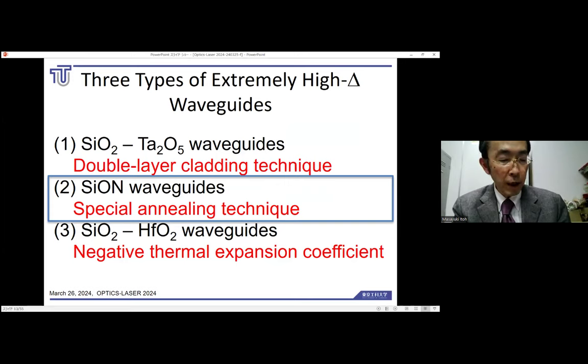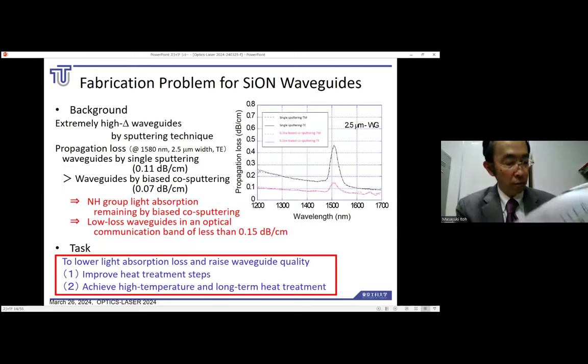Next, I will discuss silicon oxynitride waveguides. Silicon oxynitride waveguides have a long research history. However, let us briefly review the history of our research to date. We have been studying extremely high delta silicon oxynitride waveguides fabricated by sputtering and when comparing optical properties by the deposition method. If we take the wavelengths on the horizontal axis and the propagation loss on the vertical axis, we find that the propagation loss can be reduced by bias application in single sputtering, co-sputtering, and bias applied co-sputtering. On the other hand, the NH group absorption that occurs in the communication wavelength band around 1,500 nanometer tends to increase.